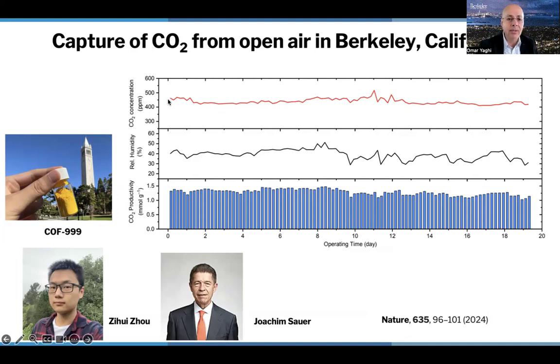Okay. This is up here in red is the amount of CO2 in the air. In the middle, you have the amount of humidity in the air. And you see here at the bottom, the bar diagram, the CO2 uptake. And the CO2 uptake scales with the amount of humidity in the air. But if you pick one humidity, you will find that it's exactly the same uptake throughout the process of doing 100 cycles. So this was a very exciting discovery because this is a durability that we have not seen in other materials. And so it was very clear that COFs are really the forerunners in solving the CO2 capture problem from air.